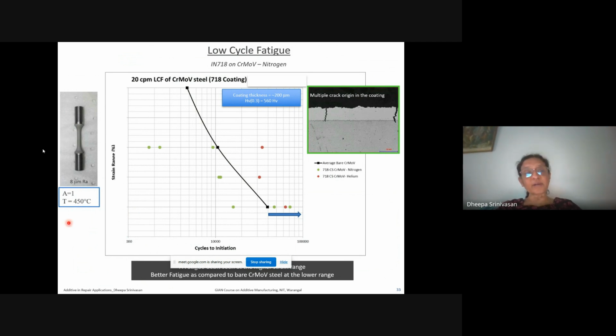Then this is just an example of one other mechanical property and a challenge that we faced. Namely, if I make a 3 millimeter coating on a substrate, there are no test techniques available to test such thick coated substrates. Normally, we make a thin coating and we assume that the substrate is of infinite thickness. All I'm trying to highlight in this slide is that the green symbols are with nitrogen and the red are with helium. Basically, at this A ratio, we had to tone down the coating thickness so much that it is seen as a thin film on the steel substrate. And the black line is the baseline number of fatigue cycles to failure for the chromoly steel.